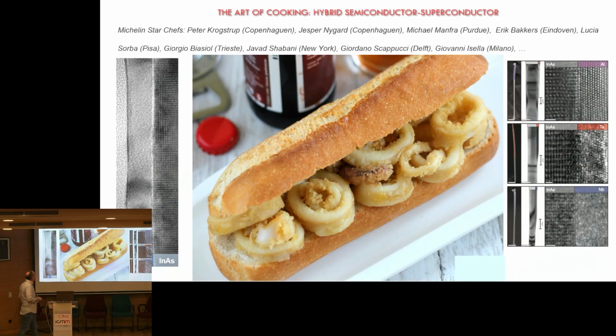And this is something we use very often: a heterostructure between a superconductor and a semiconductor, which at the atomic level, these are images of MBE samples. You can combine things like indium arsenide and aluminum, or indium antimonide. There are many combinations that you can create between semiconductors and superconductors at the epitaxial level, at the MBE level. And there are a few groups in the world that can create such clean interfaces between semiconductors and superconductors.